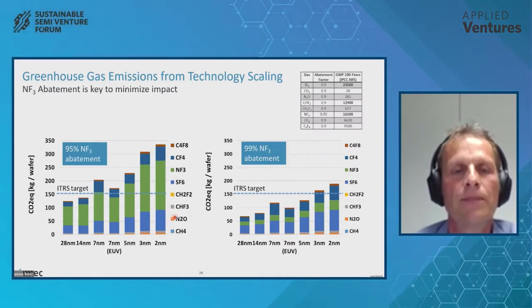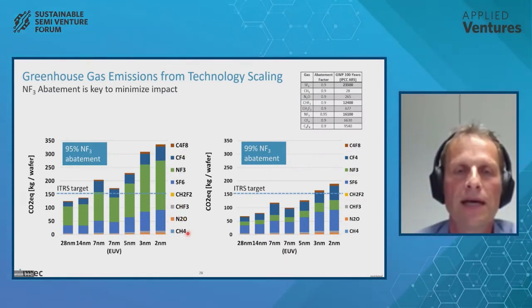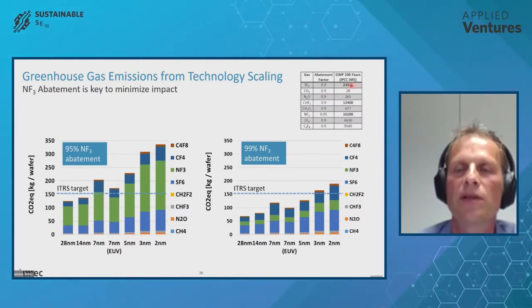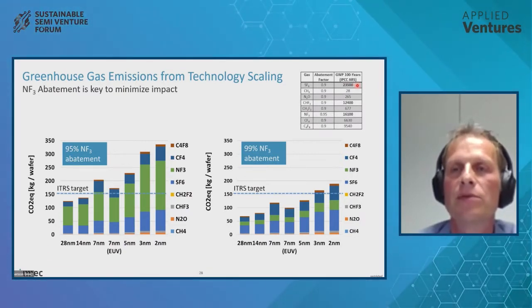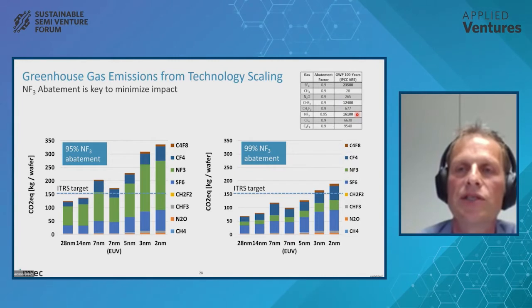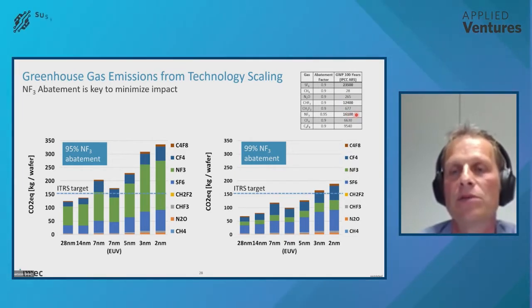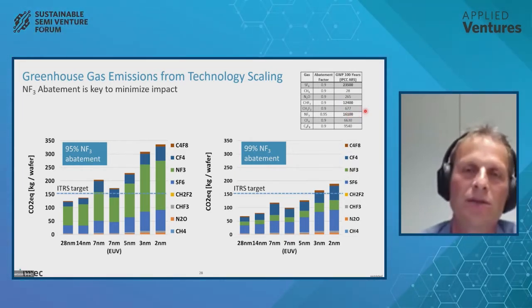So if you look at the gases that we're using in our processing, there is a wide range of gases that are very harmful in terms of global warming potential. For example, SF6 is 23,500 times the global warming potential of CO2. And CH4 is not that bad, we use quite a lot of it. And NF3 is also used abundantly in processing to clean chambers, etc. And it's 16,000 times worse than CO2.